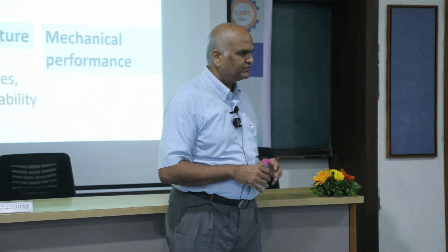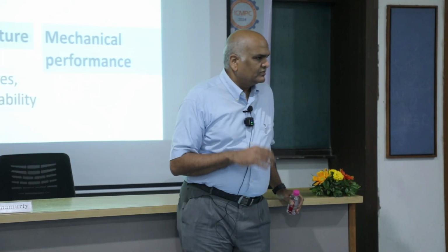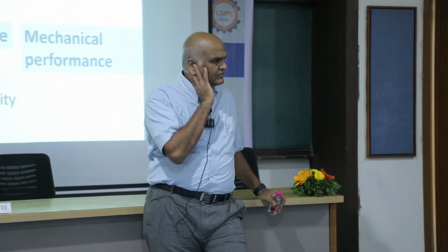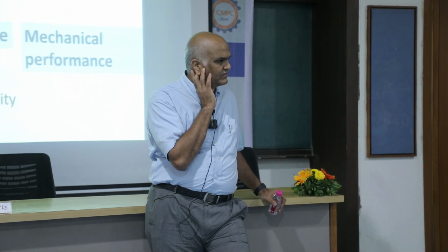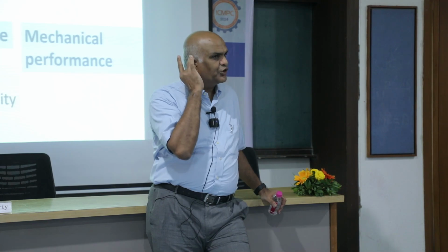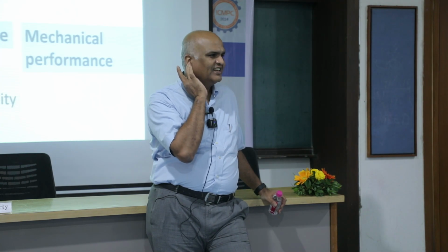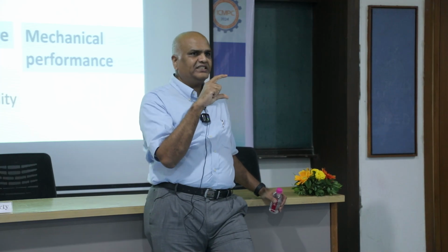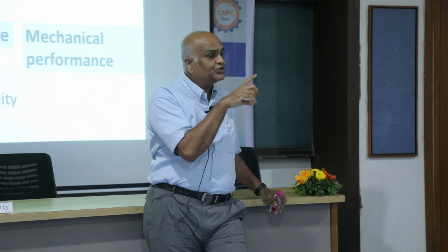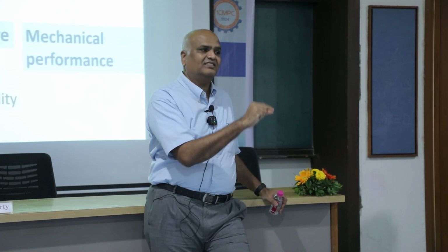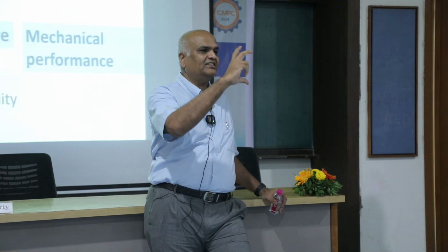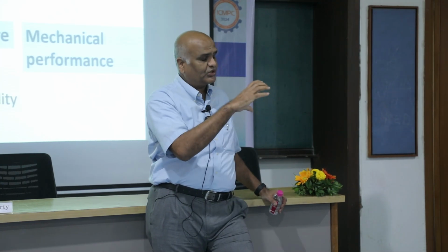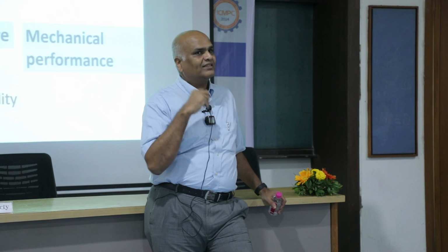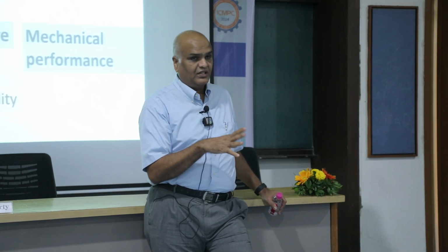Sir, the DED technology, if we compare it with 3D printers, do we see the same behavior? No, it's very different. In laser powder bed fusion, we use finer powders. Layer thicknesses are much smaller. In DED, the layer thicknesses are much coarser. You use coarser powder, much coarser also. As a result, the microstructures are different.